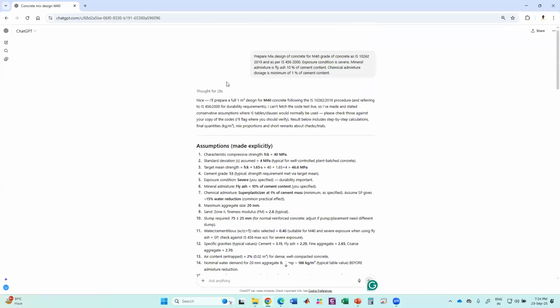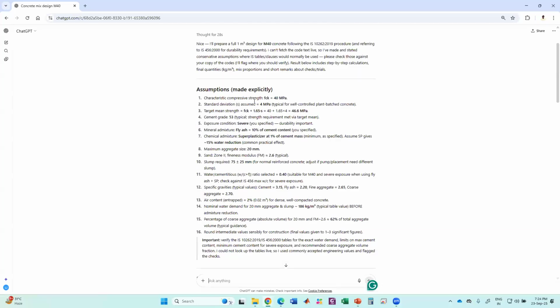So here you can see the assumptions. For M40 grade of concrete, standard deviation is taken as 4 MPa, which is not correct. Standard deviation is 5 MPa. The target mean strength is 46, it is 48.25 MPa. It automatically assumed the cement grade. Then exposure condition is severe. The durability, this is important. Fly ash is 10% of the cement content. Then chemical admixture 1% of cement mass.